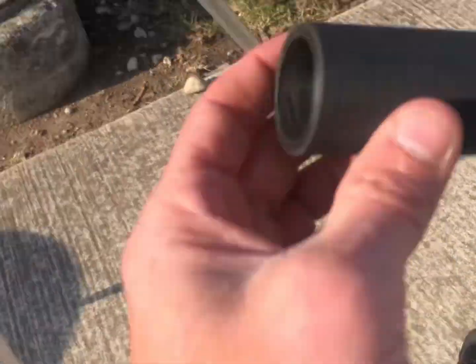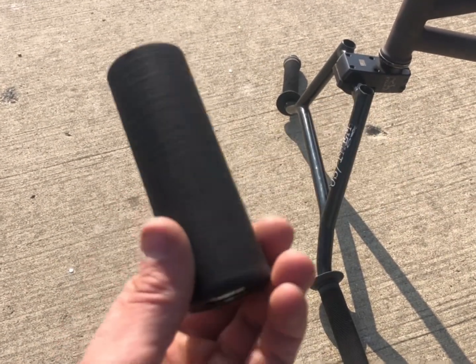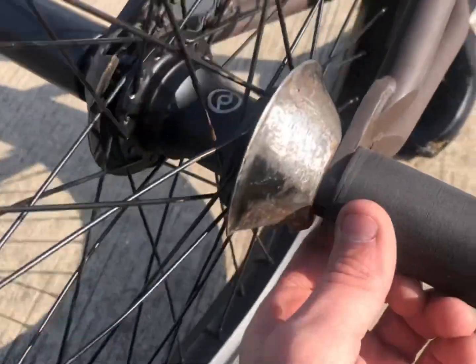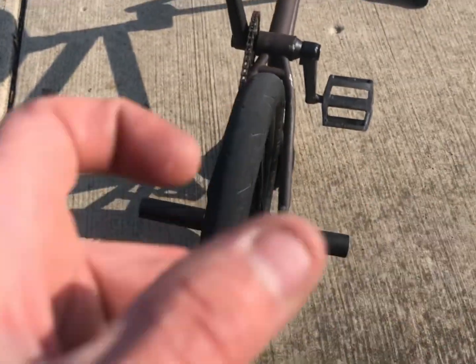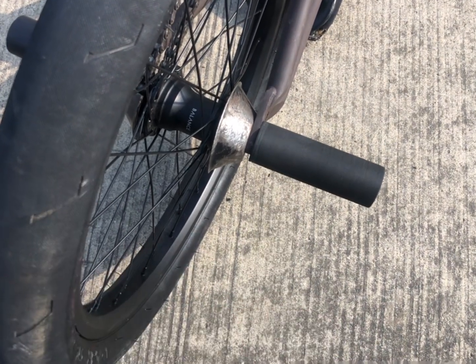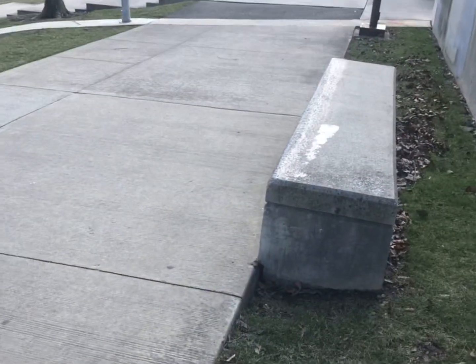That's my favorite by the way. If my axle is not broken - which it may be - we're gonna try this one right here. Gonna put on the fiberglass nylon, see how that goes. First thing I noticed as soon as I tighten this on - look at that - she's cracking. Probably because there's so much shrinkage with the nylon that it's too thin. It cracked. Now I'm going to see if I can smash it up.